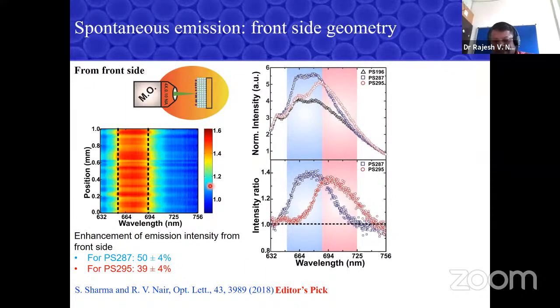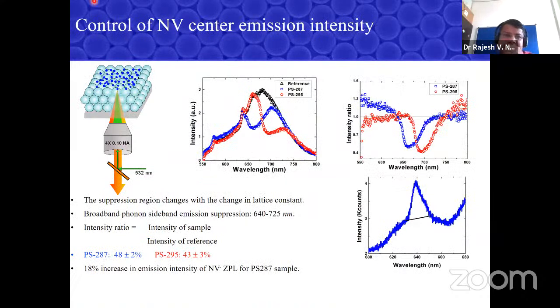So you can see that when you couple the NV centers, basically there are many NV centers here, with our photonic crystal structures, the emission is suppressed in the middle of the graph here. The black one is a reference. Again, the blue and red show the suppressed emission intensity. And if I take the intensity ratio, you can see that there's a huge intensity suppression around 650 and 700 nanometers.